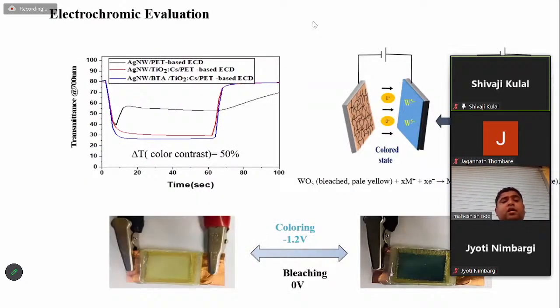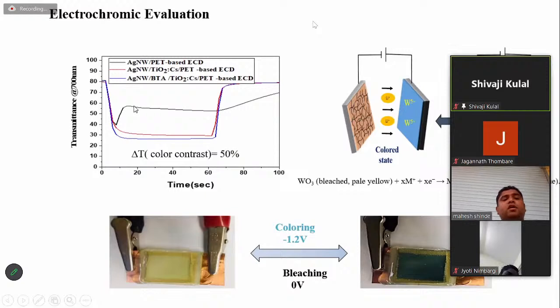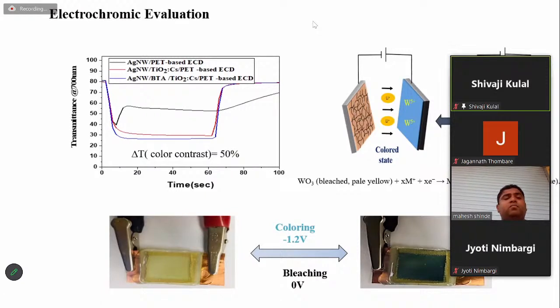We can see the transmittance from 0 to 100 and this is the time. When we apply the voltage, the transmittance is reduced from 80 to 30, and when there is no voltage, it returns to the bleaching mode. But the silver nanowire based ECD is known to be not stable: the first cycle is damaged because, due to the voltage, there is electrochemical corrosion of the silver nanowire and damage of the ECD. But in the case of the BTA and TiO2 CS based ECD, we can get about 50% coloration. So when we put this ECD indoors, we can restrict up to 50% of the sunlight from coming into the home.